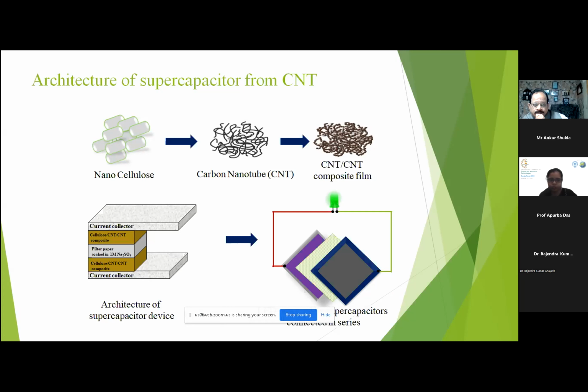Here the architecture of the supercapacitor device is seen, in which we take the nanocellulose of cotton fiber or any natural fiber, and the carbon nanotube is formed from it. That nanocellulose is mixed with the carbon nanotube to make a composite film. It is separated by a separator, and the separator is sandwiched between the cellulose-CNT composite films and the current collector. Then the architecture of the capacitor device is formed.